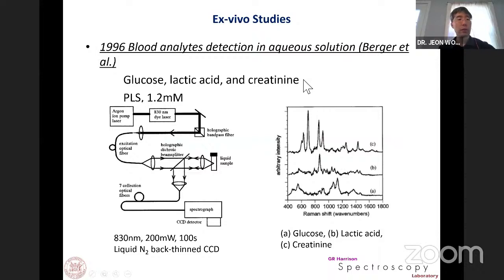Our laboratory started working on non-invasive glucose monitoring using Raman spectroscopy more than 25 years ago. Initially, we were trying to measure the glucose concentration from aqueous solution. Even though we are mostly focusing on glucose, this method can be applied to other blood analytes, such as lactate or creatinine. We could measure the Raman signal from aqueous solution with about 1.2 millimolar concentration. For glucose, 1 millimolar concentration corresponds to roughly 18 milligram per deciliter, so this is slightly higher than 20 milligram per deciliter concentrations. And these are the signals of glucose, lactate, and creatinine, which do not have much overlap with water or other surrounding materials.